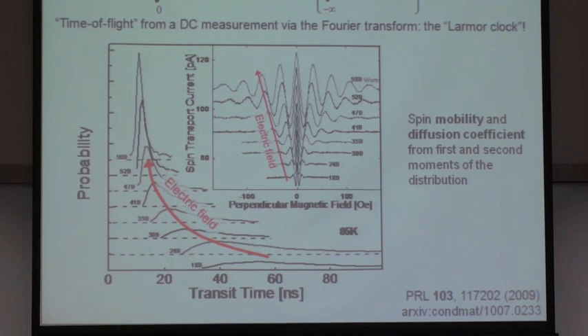At the same time, because it takes a long time for the electrons to make it from the injector to the detector, the effects of diffusion are very strong, which gives rise to very strong dephasing. And that's why we only see a few oscillations before the signal just completely washed away. As we increase the electric field, though, what happens is, well, several things.